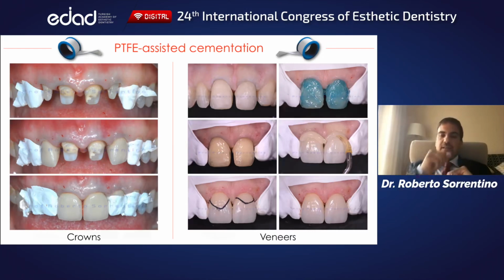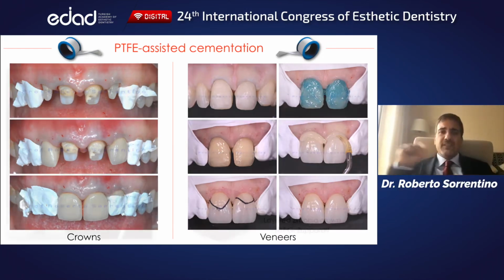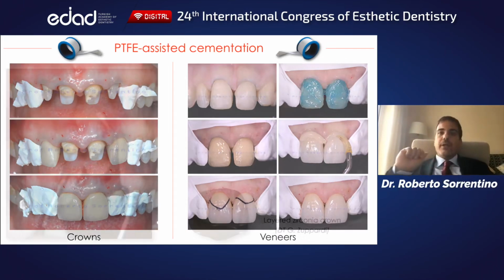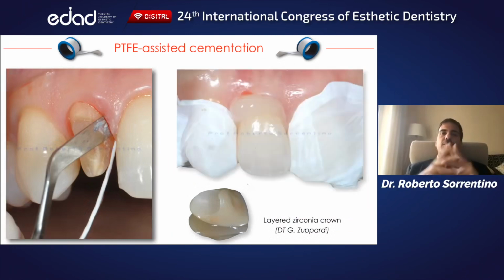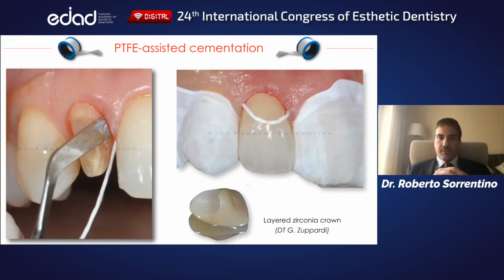In this slide, you can see a little trick. You can fabricate very thin and gentle waterproof retraction cords just by rolling a piece of Teflon tape and inserting it within the sulcus. You will displace the gingival tissues, preventing any contamination by the intracrevicular fluid and resin remnant entanglement at the same time. Very, very useful if you are using self-adhesive resin cements.